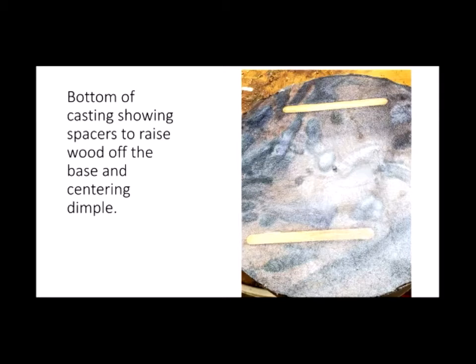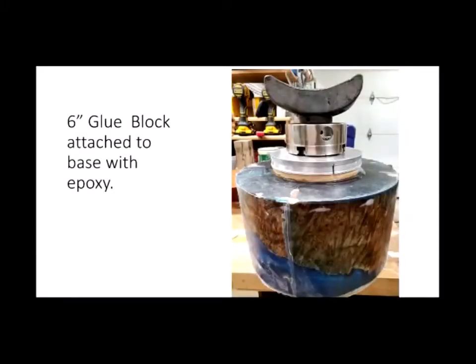where the little hole in the base was, and that's my centering point for my glue block. So almost 100% of the time when I'm doing a blank like this, I use a glue block. I do not trust the resin to create a tenon for me to hold this. Plus, I don't want to lose that depth creating a tenon. So like I said, this blank was 35 pounds, and I was going to core it, and coring puts a lot of stress on a tenon.